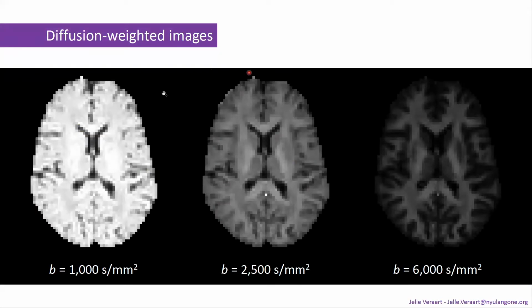I just plot the same image, the same subject. We acquired about 30 diffusion-weighted images at different B values: 1000, 2500, and 6000. And at B1000, it's actually very difficult to see contrast even between the gray and the white matter. We go to B2500, we start seeing stronger contrast between the white and the gray matter. We see a little bit more structure in the white matter itself. But if you go to B6000, you can see how clearly this map highlights the white matter with very strong contrast. And this is kind of getting some feel for the importance of using B values as a filter of axons.